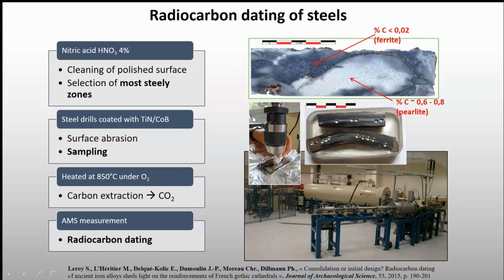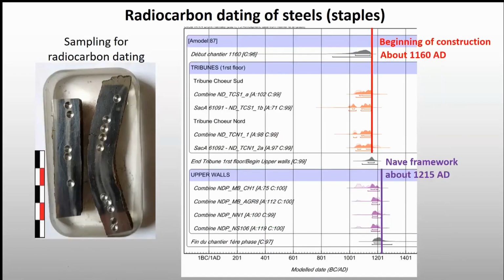So the point is to make this metallographic analysis, as we've seen before, to discover the ferritic zones and the steely zones, and then to look for the carbon in the steely zones and to sample it with a drill, preventing any pollution in these bands. So here, for example, or here on the samples of Notre-Dame, here you can see the holes that were made to get the steel from which then the carbon is extracted and then dated. So we have some results on 8 samples, mainly staples, but also two nails I'll show afterwards.